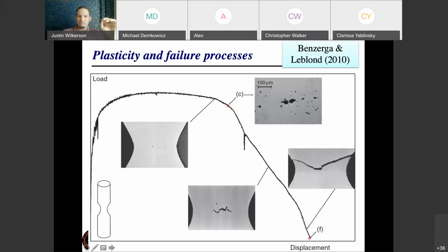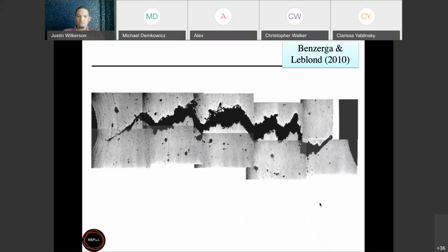So I keep loading past the ultimate tensile strength, and it's not until I get way out here that I first start getting a lot of damage nucleation. So I'm getting voids nucleating. At this point in the load displacement curve, I have even more voids. And then down here, I start getting a lot of coalescence, and the material is losing its load carrying capacity very rapidly as these voids start to link together and form a big crack in the material. And it loses all load carrying capacity when that crack runs all the way across the specimen, and you get this kind of cup-cone type fracture. It's just a zoomed in picture of it.